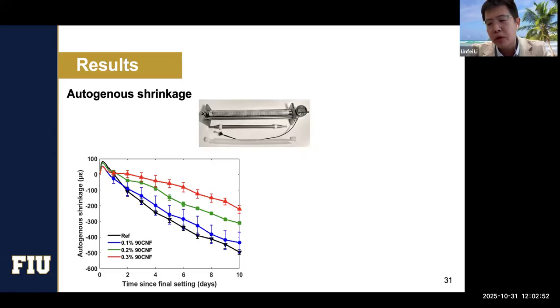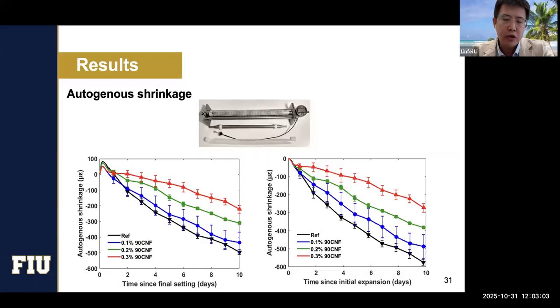And we talk a lot about that. We thought that might be because of the bleeding issue of the cement at the beginning. And if you just cut off the initial expansion, it'll be more clear to see the difference between not adding CNFs and adding different dosages of CNFs.